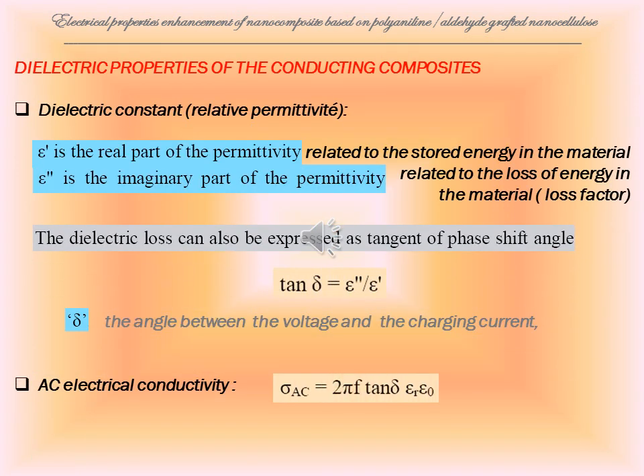The real part of the permittivity is related to the energy storage in the material, and the imaginary part of the permittivity is related to the loss of energy in the material, the loss factor. The dielectric loss can also be expressed as the tangent of the phase shift angle, tan delta, equal to the imaginary part over the real part of the permittivity.